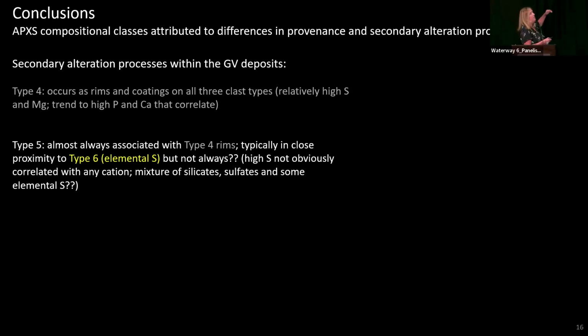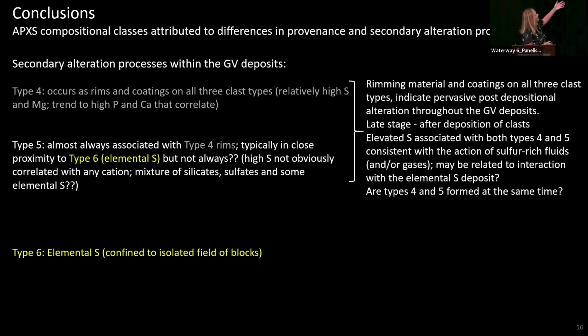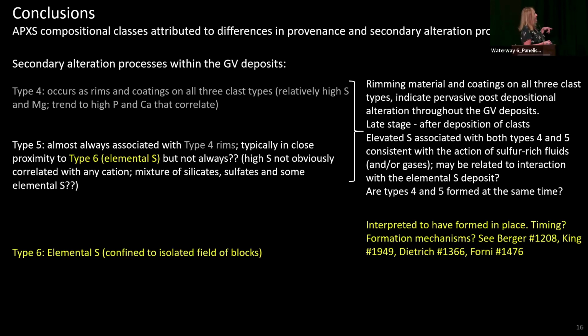And in particular, the type 4 material occurs on all 3 clast types. The type 5 material is almost always associated with that type 4 rim material and is also often in proximity with the elemental sulfur. So the rimming material appears to be pervasive, and there's elevated sulfur associated with it, which we think means that maybe there's some relationship to the elemental sulfur. And hopefully you heard the talks on the elemental sulfur this morning, and I'll leave it there.